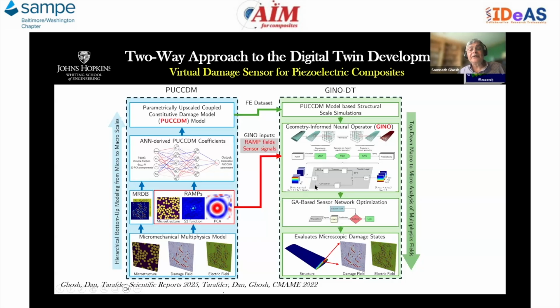And the important thing here is I'm going to be placing equivalent sensors, okay? These can correspond, for example in this case, to electrical field measurements at selected points on the surface. We have developed a genetic algorithms-based sensor network optimization tool to generate the optimal location and numbers of these sensors. So from a limited number of sensors, we can generate the full field state variables in the computational domain. That's the top-down macro to micro analysis. So the first part is to focus on the generation of this PUCCDM.